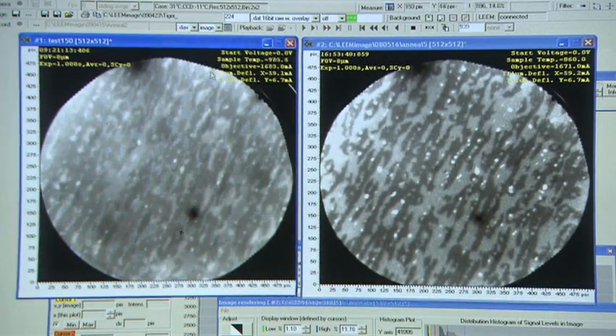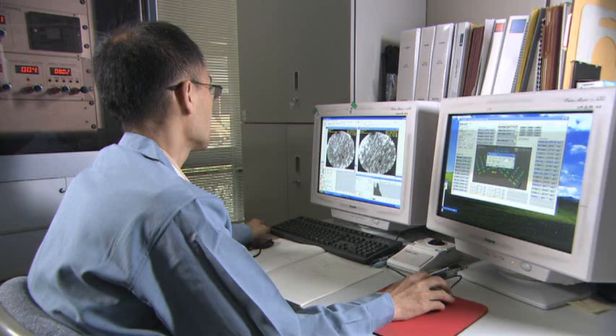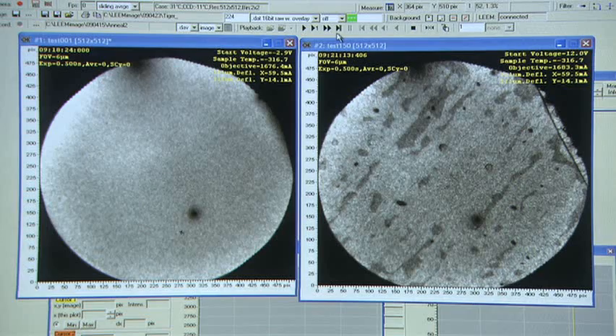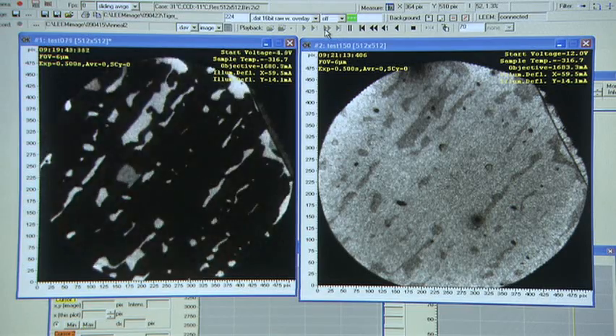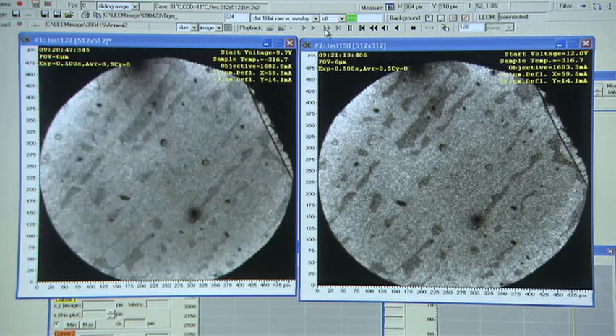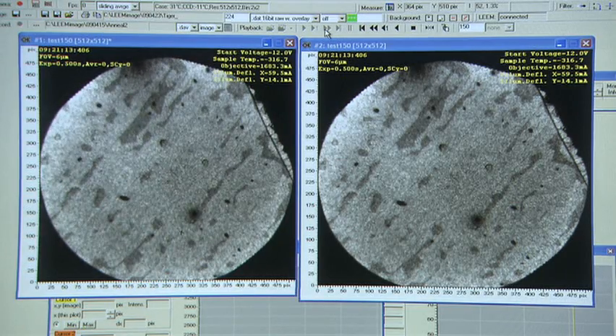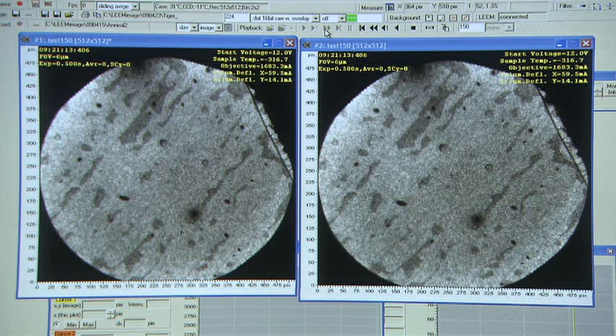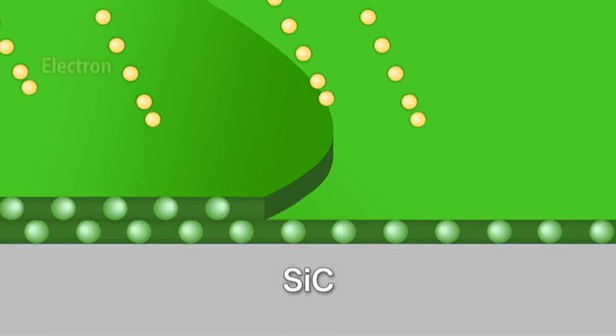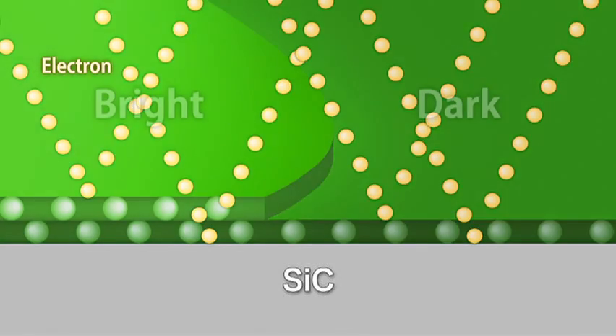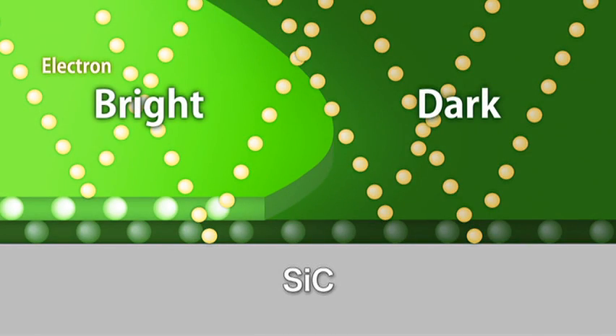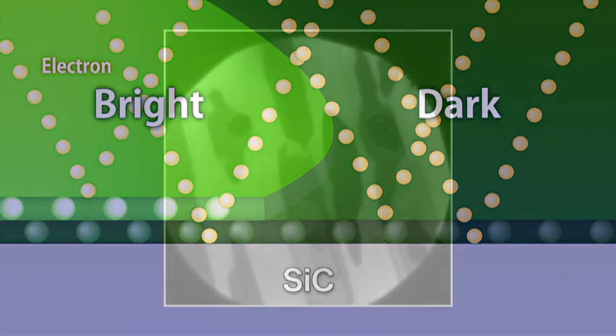NTT Basic Research Laboratories is making use of this equipment to grow graphene and to analyze the conditions required for growing. So far, we have established techniques for the microscopic determination of the number of layers, making it possible to fabricate the samples necessary to study their characteristics.